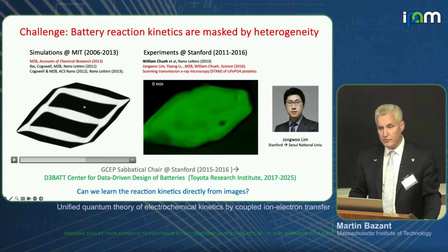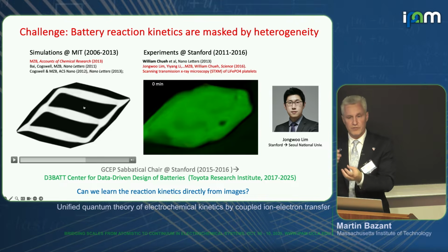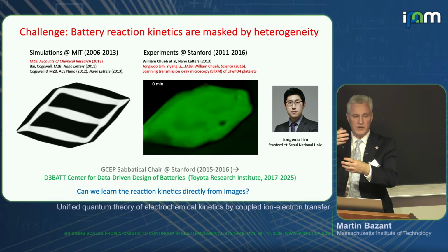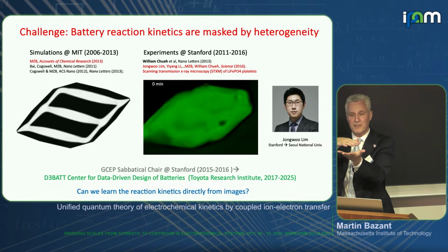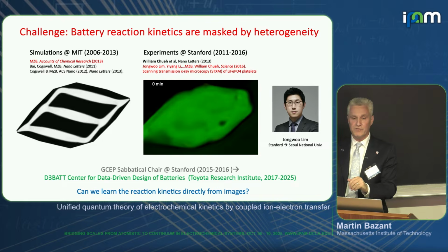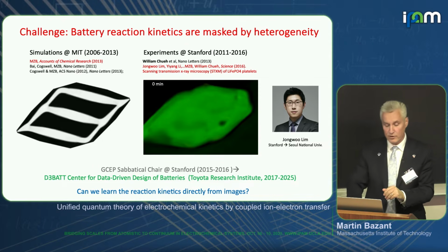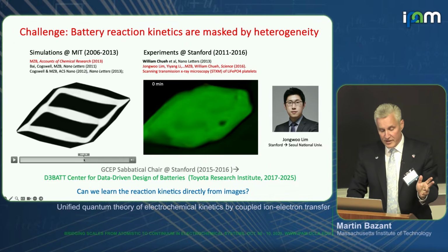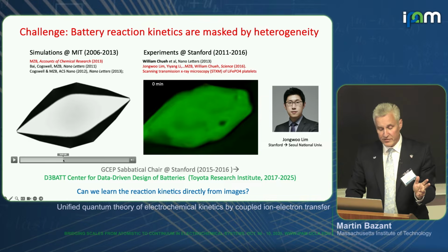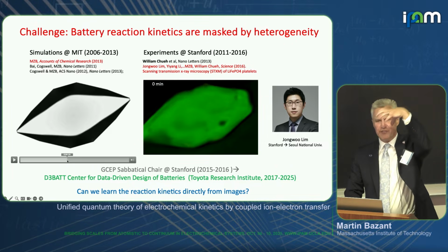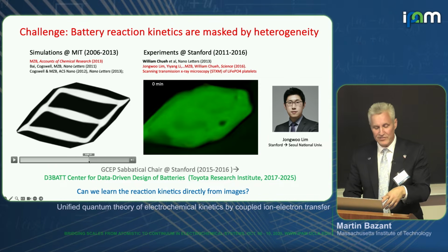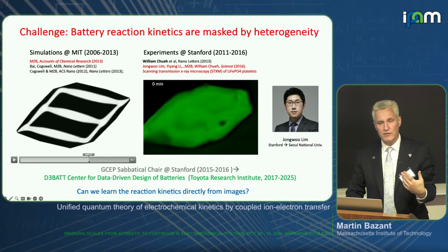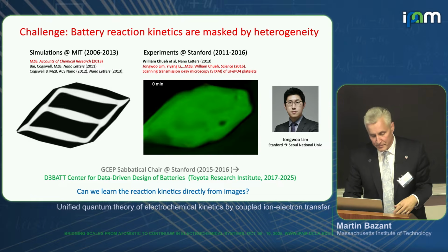The second thing is the two phases have different crystallography. When the lithium is inserted into the high density phase, the lattice unit cell expands in two directions and contracts in the third. That leads to very complex mechanics. If a phase transition happens inside a particle, that's what you're seeing here: at first it nucleates on the boundaries, but now it's like a balloon being squeezed from the outside, and at some point it can't handle it, and it breaks into these stripes to minimize elastic energy. So that's what we predicted.